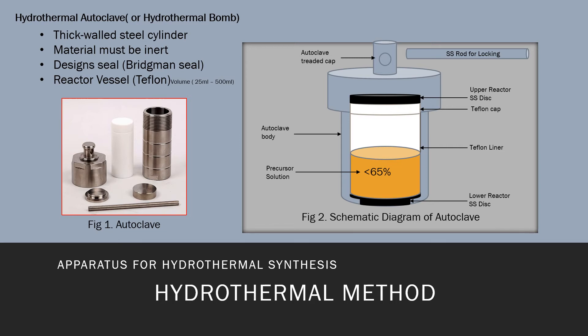The important part of the precursor solution in the reactor vessels, you can see in figure two, the volume of the precursor solution must be less than 65 percent of the volume of the vessels. That's all the information about the equipment for hydrothermal crystal growth.